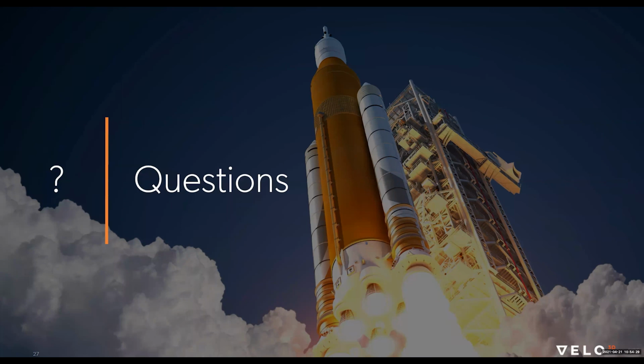All right. Do we have any design guides? Yes, so we have the Velo3D design guides. We have a series of YouTube videos as well where we discuss these. But yeah, because we don't run into recoater clash issues, because we have a non-contact recoater, and we're able to print at much lower angles than 45 degrees, generally down to 0 to 10 degrees based on the geometry, the residual stress and the structure stability play a greater role. So we have several plots out there of minimum angle as a function of geometry shape. And that helps design engineers and manufacturing engineers alike to really get the optimal solution from Velo3D's technology.